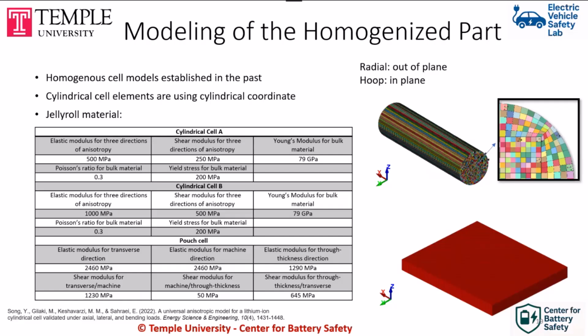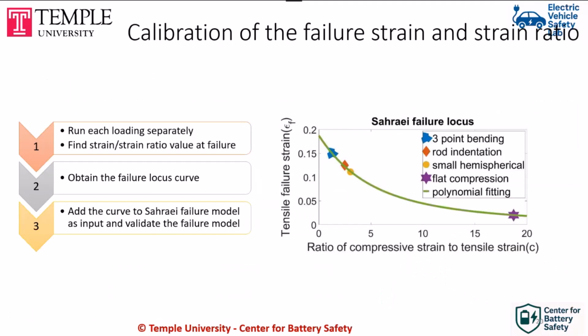So once we have this coordinate set up, then we can use it for the cylindrical cell, and then for pouch cells it's very easy because the layers are aligned with the global coordinate system. So now we use the Sahraei failure criterion, calibrating each of the load cases with their ratio of compression to tension and the tensile failure